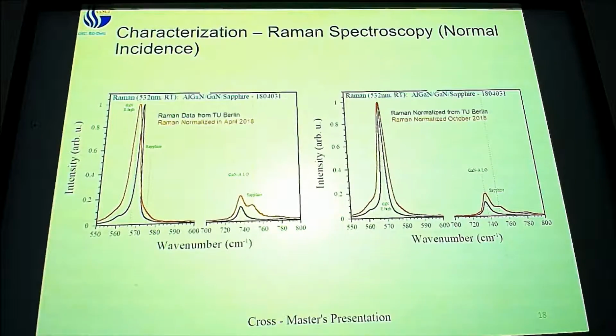And a couple months later, I realized I needed to actually make sure that I was doing a good job, and I plotted the same results with the same sample again, and you can see with my calibration, we shifted them right over, and it worked. So this system is now calibrated, even if it wasn't back in April. That being said, the results that we usually take away from this are difference measurements. So even though a peak may be shifted, the difference between two positions on that peak do not vary significantly. So most of the measurements that we made with this system are not called into question. It's just a little bit more accurate now.